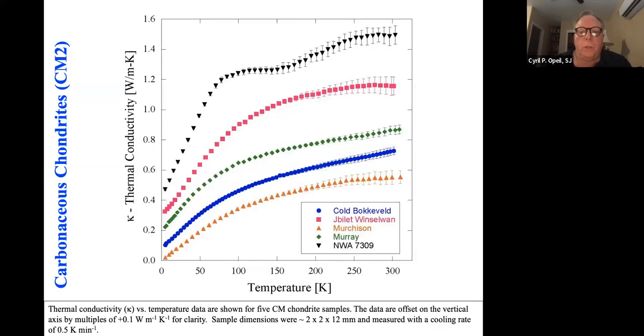The next slide here is thermal conductivity versus temperature. And again, I have, for clarity, offset the data so that you can actually see how it's changing or developing over time. It goes from a high of less than 2, at 300 Kelvin, and all these things tend towards zero. What's important to note here is that these are highly disordered materials.